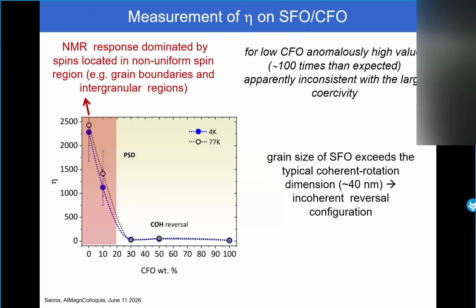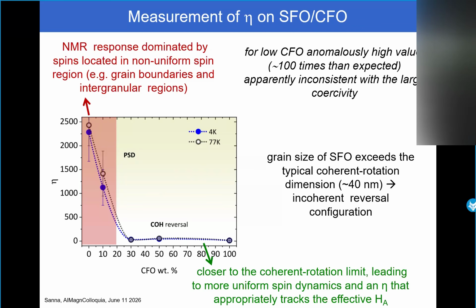So at the end of the story, this is the interpretation. The NMR response for low CFO content is dominated by spins located in a non-uniform spin region, where you have a large incoherent magnetic volume. And so the energy barrier to reverse the magnetization is lower. And this gives you a higher enhancement factor. While when we increase the CFO content, we are closer to the coherent rotation limit, leading to more uniform spin dynamics, and the enhancement factor effectively gets the appropriate value expected for hard materials.